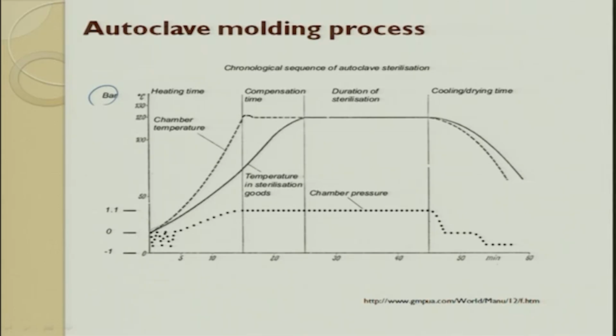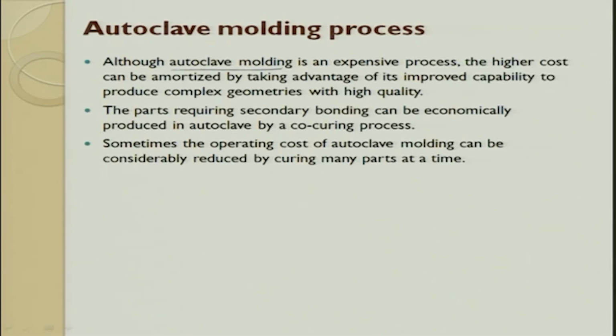The temperature initially goes high, is maintained, and then you get an output. So, there is heating time, compensation time, a duration for sterilization, that means consolidation, and then a cooling time to get the required output. Because of the autoclave, the process becomes slightly expensive, so only complex parts are made this way. Parts with secondary bonding can be economically produced by autoclave using a co-curing process.